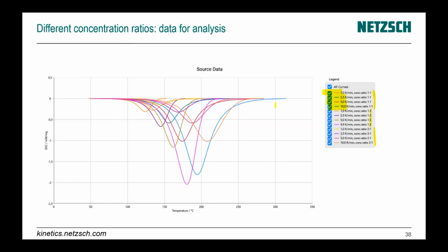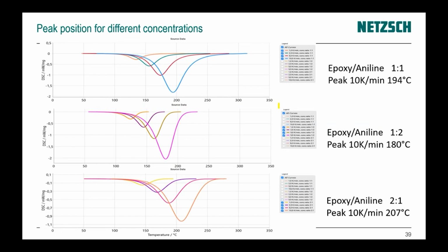If we compare this data for different ratios, then we can see that the point of maximum, for example for 10K per minute, has a totally different temperature. Here it is 180 degrees C, here 194, and for the epoxy to aniline ratio 2:1, we have 207 degrees C. So the position of the peaks is totally different. The concentration has an influence on the reaction rate. It is the first point.